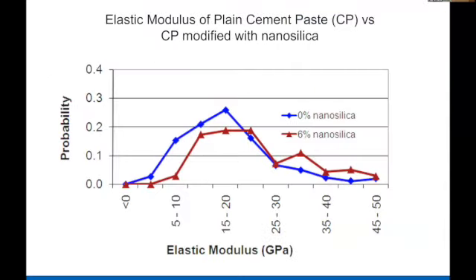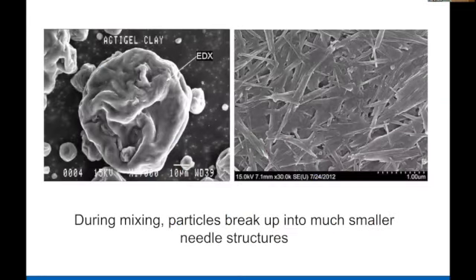And so here I've shown the results from the nanoindentation. You can calculate the modulus using contact mechanics, and plotted is the elastic modulus in gigapascal versus frequency of that observation, or probability. And you can see from this frequency curve that when you have nanosilica, the curve has moved toward the right. That means higher stiffness of CSH, as shown from the SEM analysis. So that's the difference. So now I want to talk about another interesting nanomaterial, and that's nanoclay.